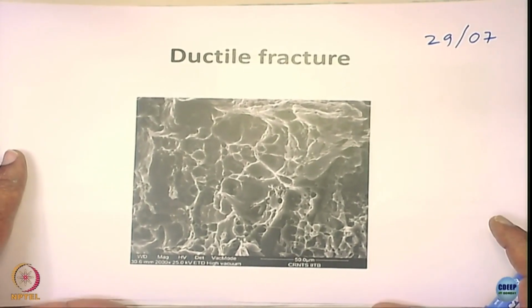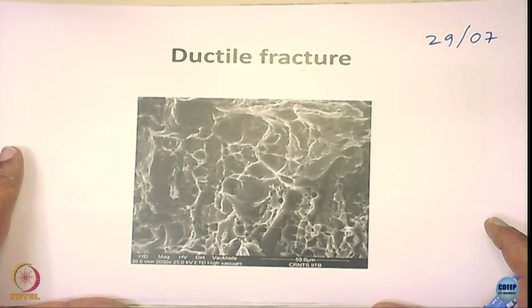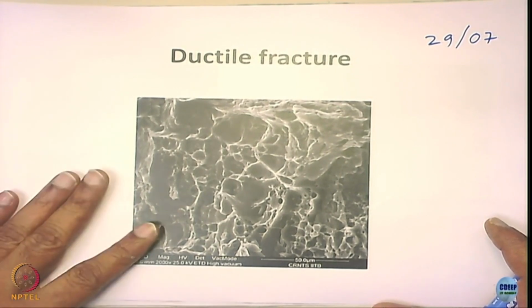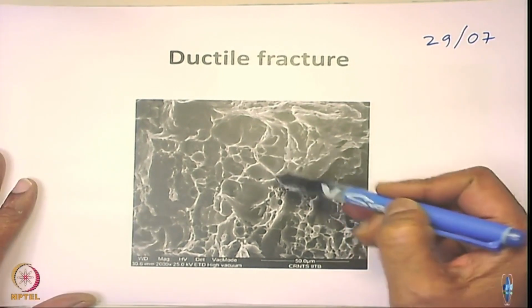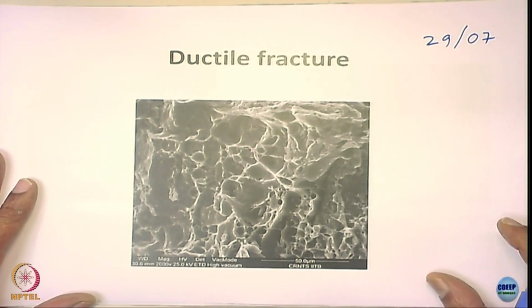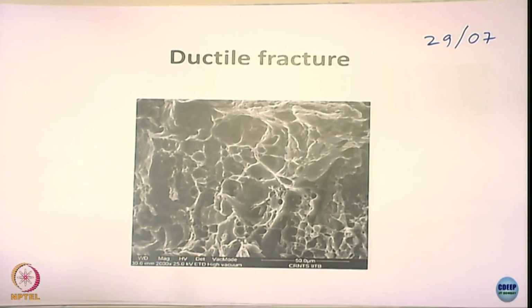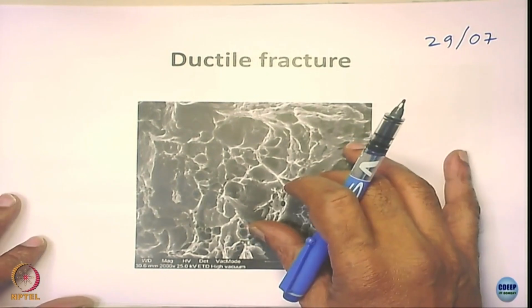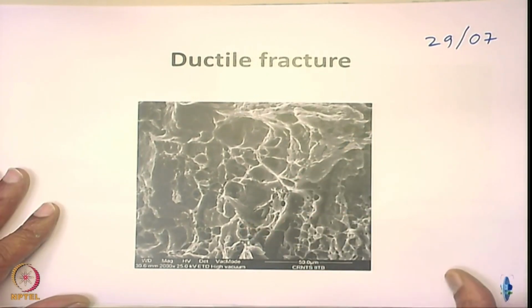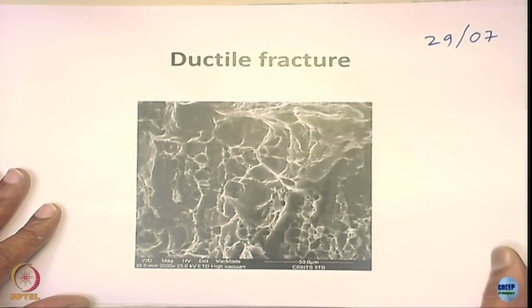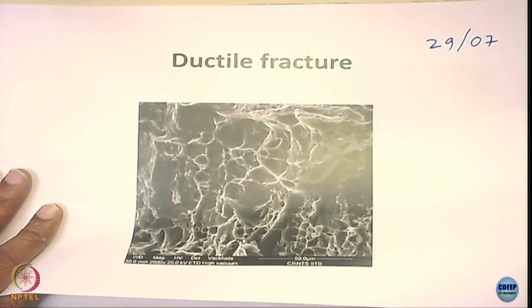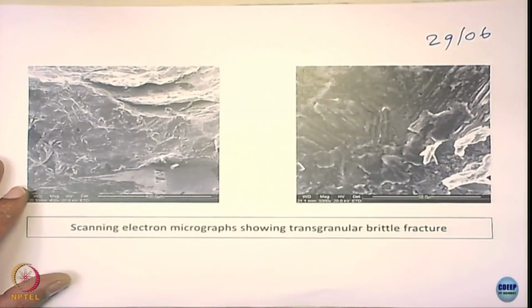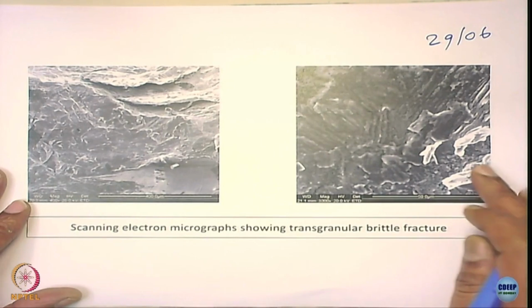This is a material failed in air, in the absence of environment. It is a tensile failure, and I hope you can see this. It is called a fibrous failure, a dimple failure, a dimple fracture. And you can see the fibers. The metal has nicely elongated, they just flowed nicely, right? So this is a kind of ductile fracture, when you have simple failure in air. I suppose that the other one looks like glass that failed here.